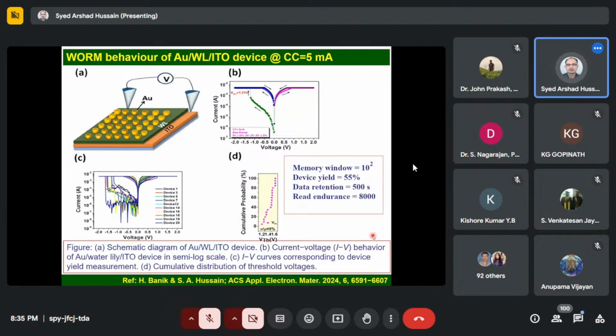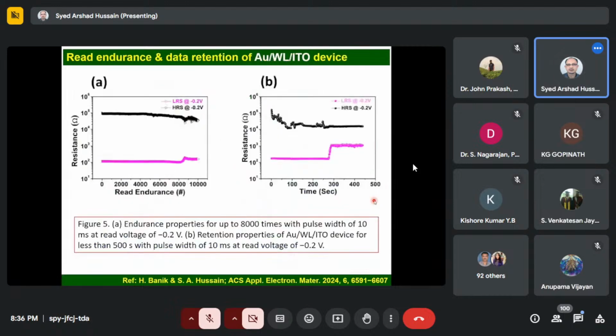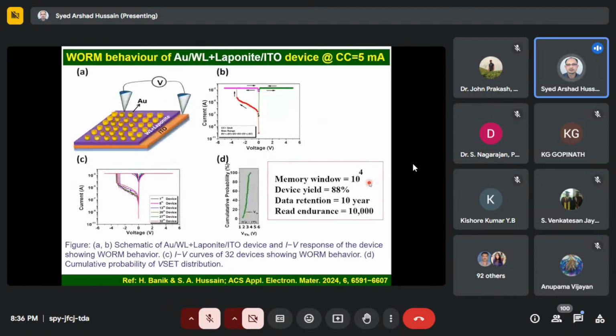So this is the device in the absence of clay. It shows WORM behavior with a memory window of 10 to the power 2. Device yield was not very good, it's 55%. Read endurance around 8,000. These are some characteristics of endurance and retention.